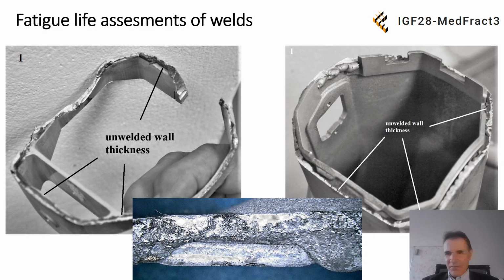These e-bikes have a modification of the thickness of this tube around the circle, around the surface, and on this picture it is very well visible that in some parts the material is well welded, and some part is very insufficiently welded. This is an additional problem for the assessment of fatigue lifetime, because it's very complicated to determine the appropriate fatigue properties of the material of this joint.